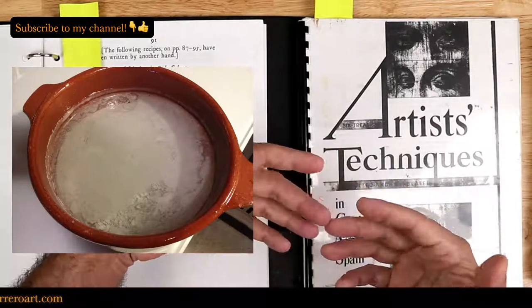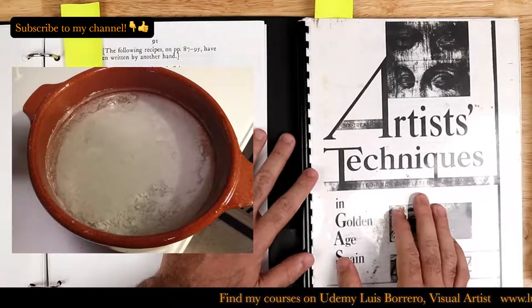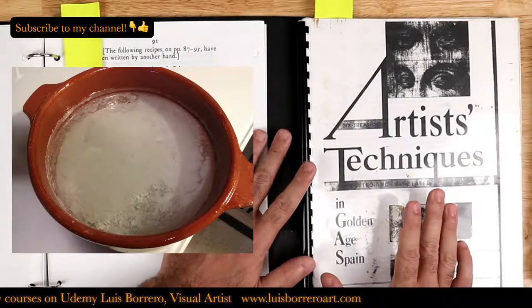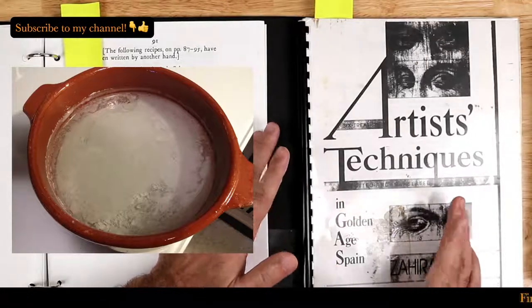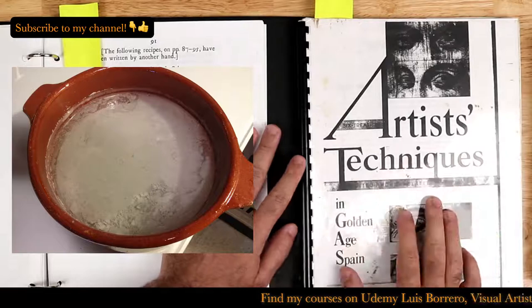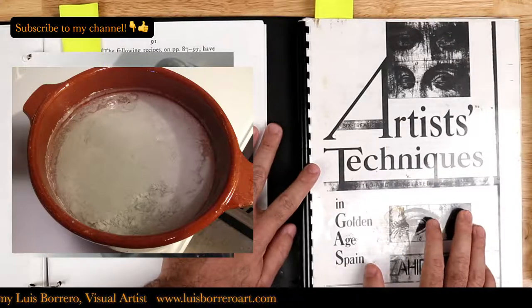Now, what happens if you don't wash the pigment? Well, you get some severe yellowing in your final paint, which is not good. So you have to wash this pigment very thoroughly, and manufacturers, as a matter of principle, would do this. But in the old days, it doesn't seem that was the case, as is described by Pacheco and Cennini. All right, so let's just move on.